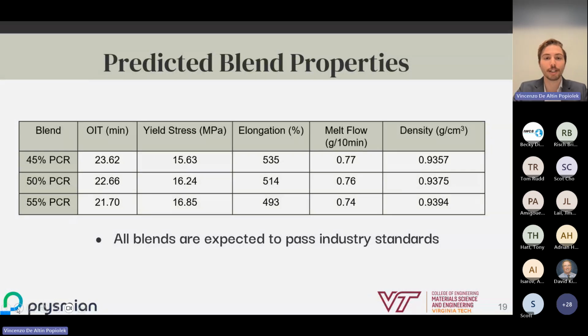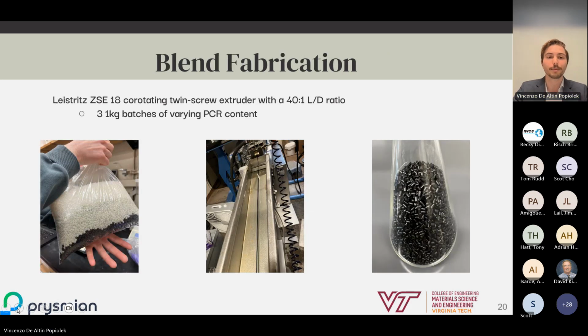Finally, using these criteria in our initial characterization results, we were able to create a 50% PCR blend along with a 45% and 55% PCR blend to simulate variation around that 50% target. Using the rule of mixtures, we were then able to predict the properties of these blends, and as they were expected to pass industry standards across the board, we moved forward with our blend fabrication.